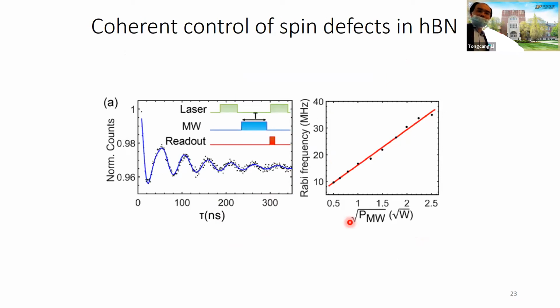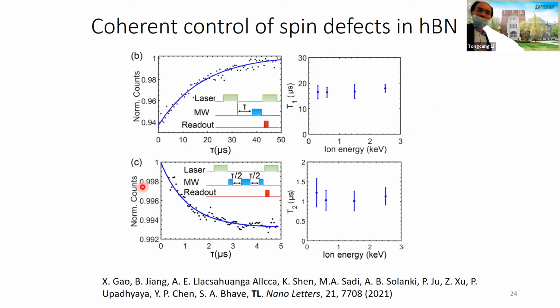We can also measure the coherently controlled spin. Here is a Rabi oscillation. By controlling the microwave power, we can change the coherent oscillation of the spin. For people who don't know the purpose, you can apply this like a quantum NOT gate. You apply, for example, a pi pulse, and you can flip from spin 0 to spin 1. So you can do a NOT gate. We also measured T1 to be about 17 microseconds, and T2 to be about 1 microsecond. But there are some debates right now. Some people also produce different results, and this is still ongoing.